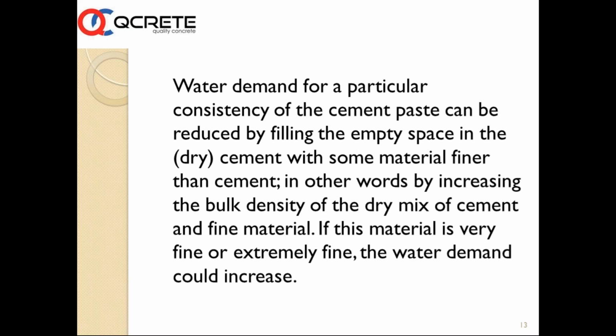One is silica fume, which has been used, but with silica fume the water increases because it's too fine. Then we have certain materials which are not so fine. When we use some of these, 10 to 15%, water can decrease to some extent.